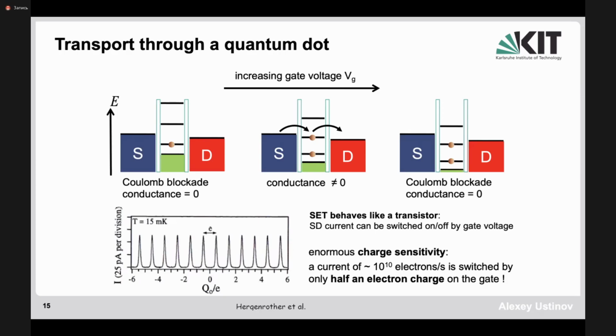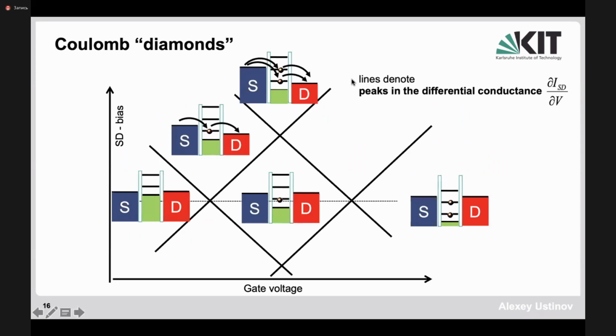So this is the operation of the single electron transistor, and what you do basically, you apply two voltages. You apply source drain voltage and you apply the gate voltage, and then you start from having no electrons on the dot. This will be this area and this area, and then if you cross this line in this diagram, then you have one electron in the dot. If you go further up, you will have 2 electrons in the dot, and so forth. But then if you go horizontally, then you could sort of lock the electron inside the dot and then do something. And basically all these regions characterizing different numbers of electrons in the dot are characterized by these peaks of currents, which are due to the increase of the tunneling current when we have a situation that the dot state is exactly between source and drain, and some current is applied between source and drain.